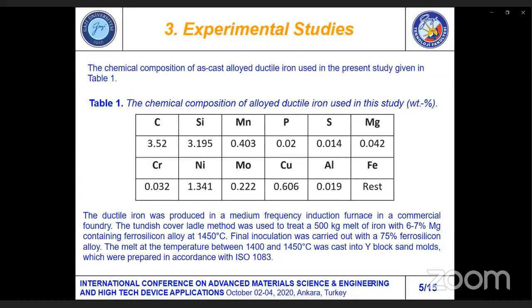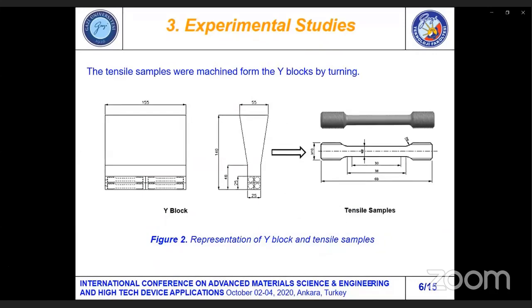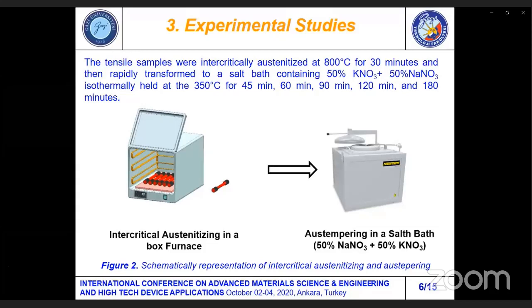The melt at a temperature between 1400 and 1450 Celsius was cast into Y-block sand molds, which were prepared in accordance with ISO 1083 standards. The tensile samples were machined from the Y-blocks by turning. You are seeing the tensile sample position in the Y-blocks. The tensile samples were intercritically austenitized at 800 Celsius for 30 minutes and then rapidly transferred to a salt bath containing 50% sodium nitrate plus 50% potassium nitrate. The salt bath is isothermally held at 350 Celsius for 45 minutes, 60 minutes, 90 minutes, 120 minutes and 180 minutes.